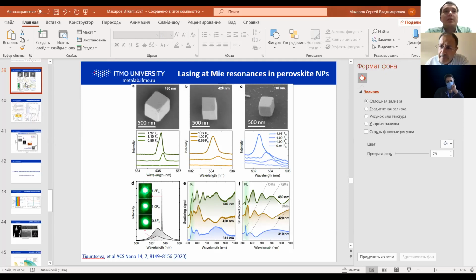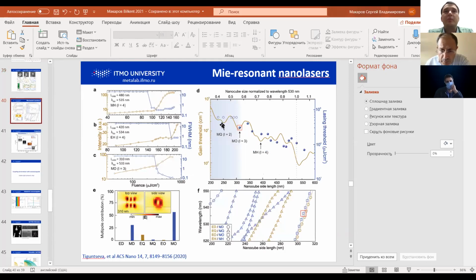Yes, you're absolutely right. I think we can go even to the quadrupole resonance. As you can see here from our calculation, the next minimum is around here, but for this the thresholds are quite high due to the high refractive index of the substrate. If we make it lower, we can expect the next minimum to be around 250 nanometers, plus or minus, of course, because everything is shifted a little bit. Yeah, I guess having these cubic nanostructures sitting on a very thin film, almost a suspended architecture, could give really good results, in my opinion. Great. Yeah, exactly.